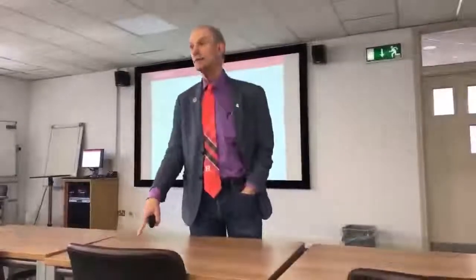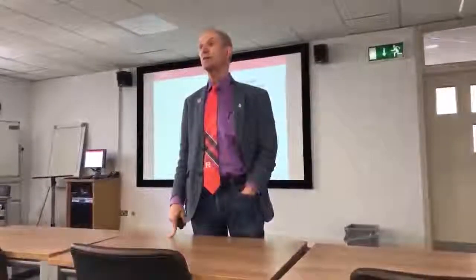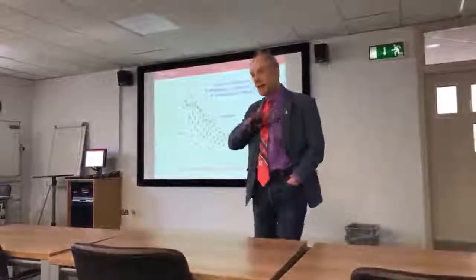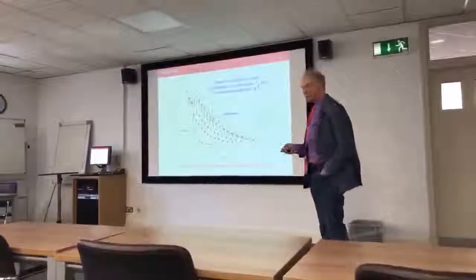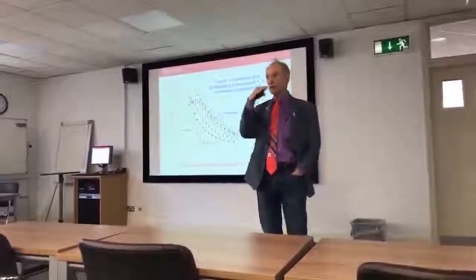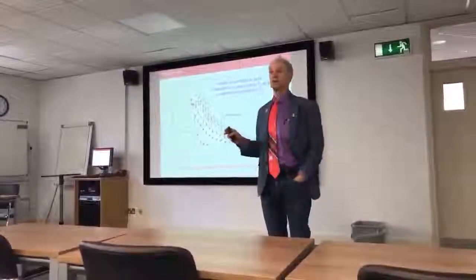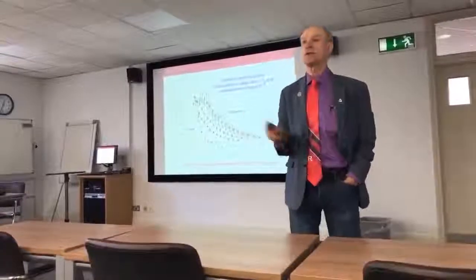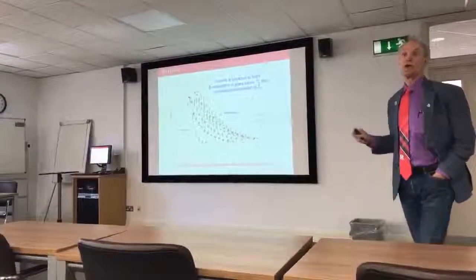These probes, in a sugar, do not provide a sensor for oxygen because the oxygen diffusion through the glassy sugar is not measurable. In other words, if we take maltodextrin and put it in an air environment and in a nitrogen environment, you can't see the difference. The probe does not see oxygen. Oxygen does not diffuse through the matrix at a rate which influences the probe.